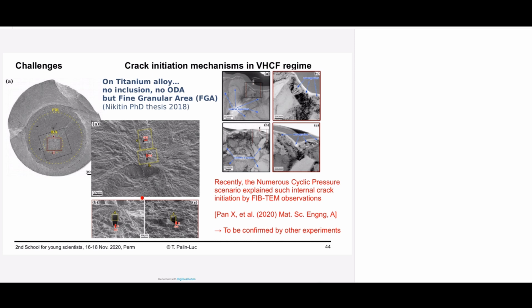We have observed in titanium alloy, by micro machining with a FIB very thin layers observed by TEM, that even if there is no inclusion at the crack initiation area, like here, you see there is no inclusion, but very close to this area, if you observe by transmission electron microscope, you can see nanograins. So it means the recrystallization exists even if there are no inclusions. So this is very interesting in order to explain why there is crack initiation without any defects. Of course, this has to be confirmed by other experiments, because up to now, we are the only authors who observed such a scenario.